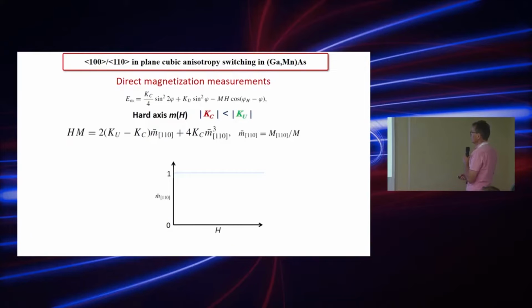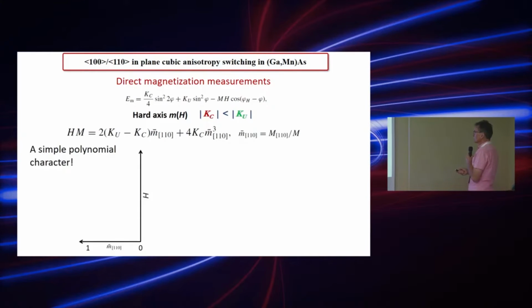So somehow we should get a dependence like that, but to get the form of this dependency, we should solve this equation, and this is a third order polynomial, and actually the general solution for such a case is very complicated, and it's not really instructive, and there is zero educational value. However, what we can do is rotate our coordinates by 90 degrees, and now we can observe that before going into the lengthy calculations of solving this third order polynomial, this expression actually relates the magnetic field with the value of m, the projection of m, and it has a very simple form. There is a linear term and a cubic term. So this is simple to analyze, but you have to plot the results in a slightly different way.